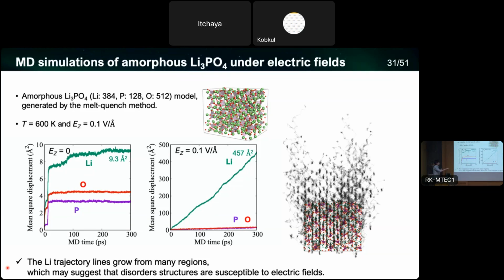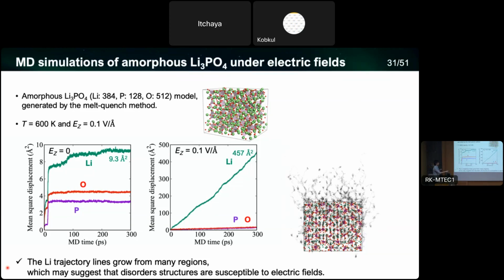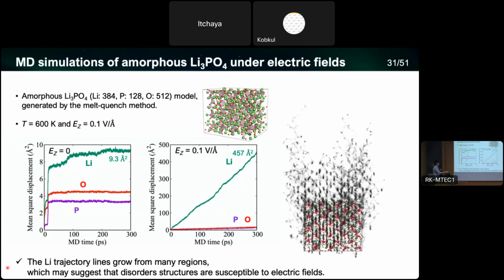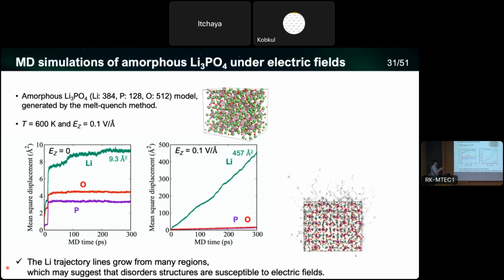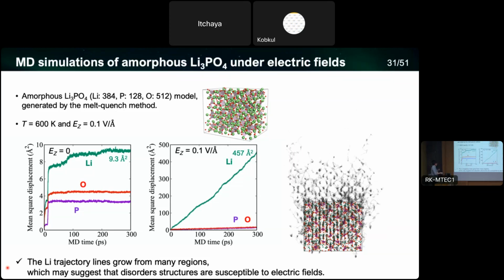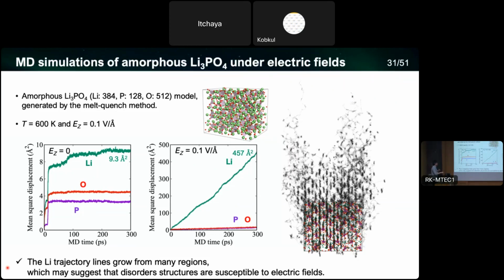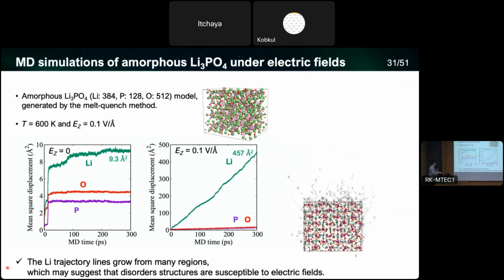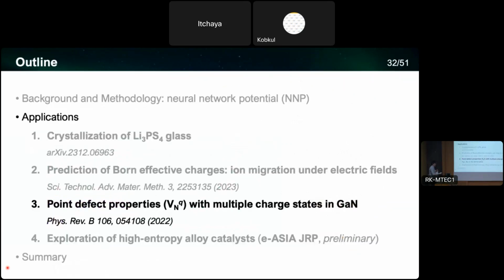And if you look at the trajectory lines, you can see the lithium is going upward along the electric field, but not limited to specific regions; from the entire region, the lithium is going toward the z direction. This is because this kind of metastable structure is susceptible to the electric field. So this is the second topic. And I will quickly go to the third topic.